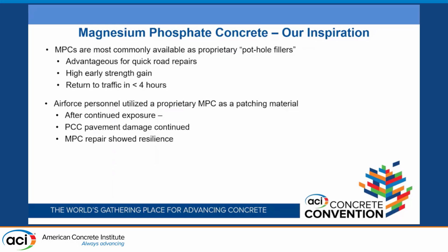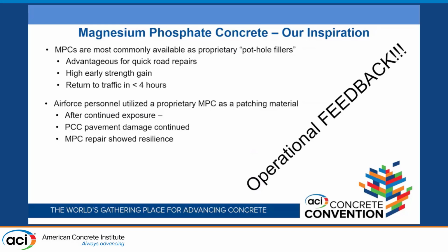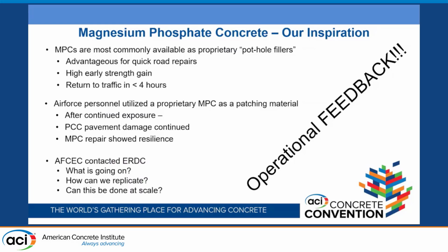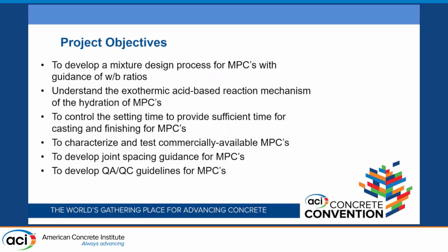So Air Force personnel were using these proprietary MPCs as a patching material. And then after continued exposures, some of them noticed that the MPC repair was performing better than the OPC, the ordinary Portland cement concrete, around it. So we got some operational feedback, and I apologize for all my animations, I went a little haywire. And then the Air Force contacted us. That's AFCEC, the Air Force Civil Engineer Center. They contacted us and said, hey, we noticed something here. What's going on? How can we replicate this, and can we use it at scale? So that was the whole birth of this project, if you will. And so we went through and developed a project, first coming up with the mix design process for MPCs.